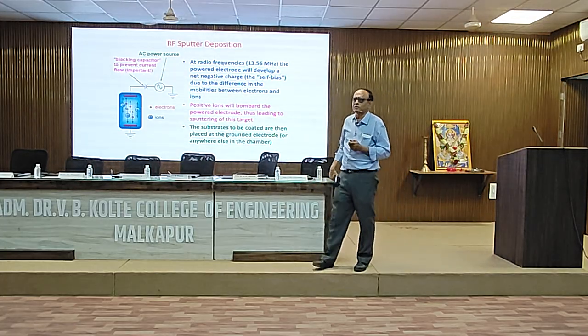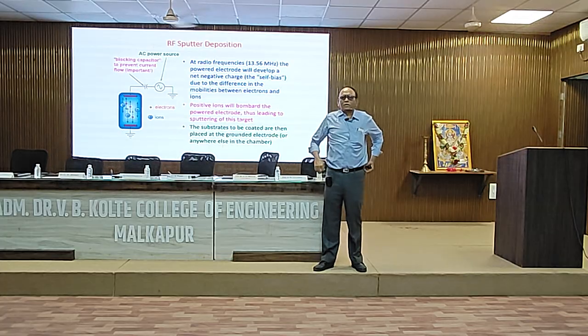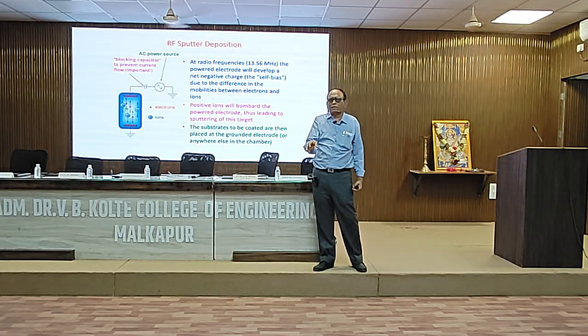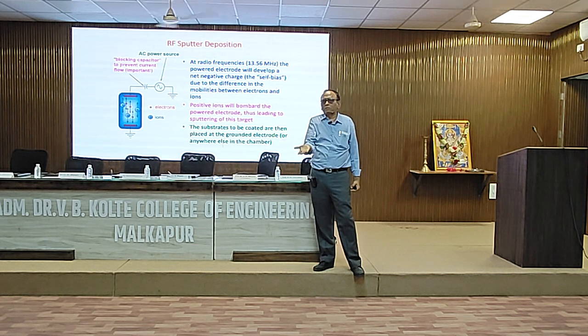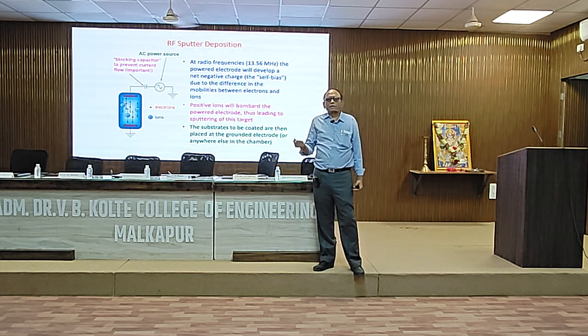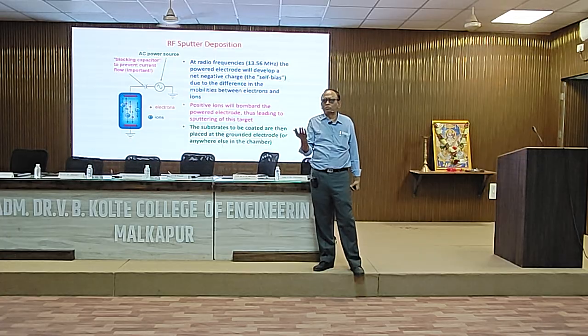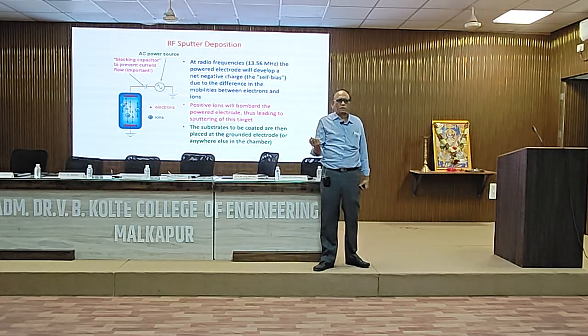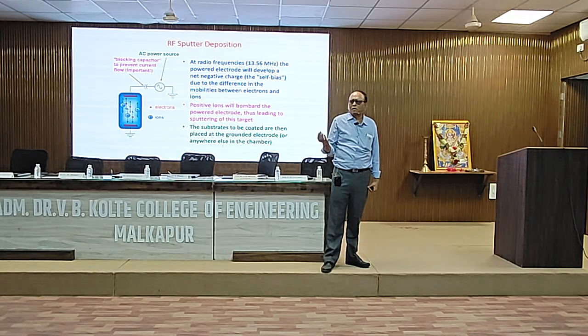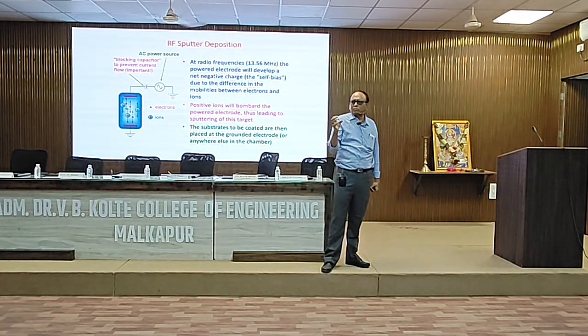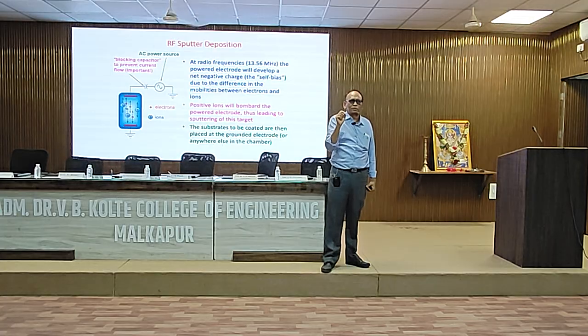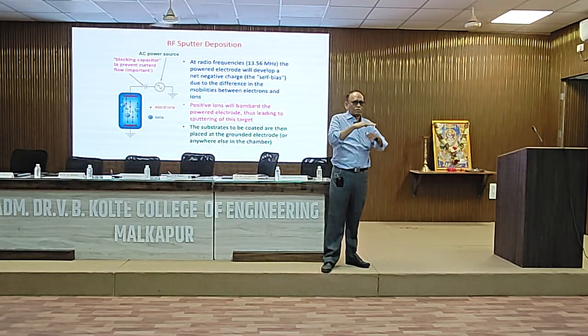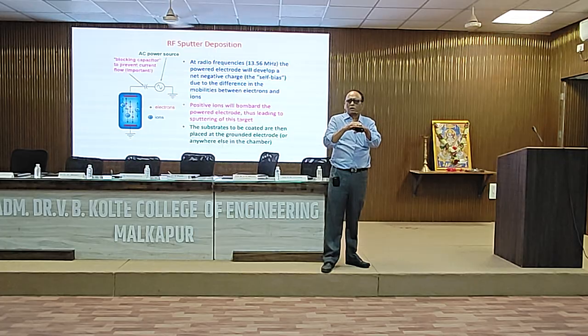Now, once this ionization is done, this ionized plasma can be used for various applications. One of the classic example is, see, your sputtering process, where you are removing the material by energetic argon bombardment and then depositing the sputtered material from the cathode. It cannot take place if your substrate is insulating. But in the semiconductor manufacturing, like making ICs and all these things, you have to have large number of insulators that needs to be processed, like deposited, SiO2, Y2O3, and all. If you want to deposit a capacitor while making the IC, then you want to sputter SiO2. There, for giving anti-reflection coating on solar cell, you need to deposit Si3N4, silicon nitride.